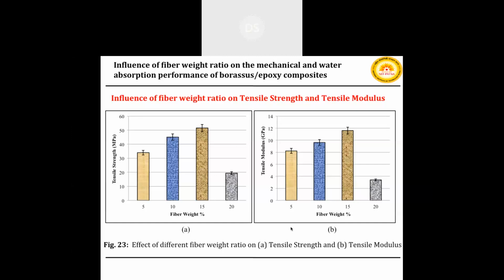In the case of fiber weight percentage of 20%, the tensile strength is approximately 20 megapascal and tensile modulus is 3 gigapascal, which decreases suddenly because of more weight percentage of fiber as compared to resin. Okay, in this case the fiber cannot get wet and resin cannot reach every position of the fiber and cannot form proper interfacial adhesive bonding between the fiber and matrix.